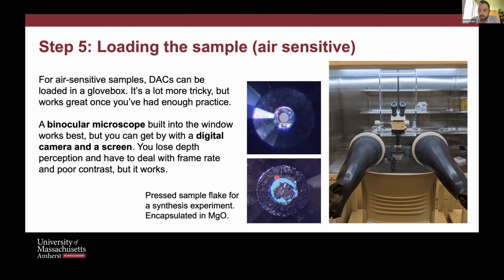I'm showing a picture. So again, this is not really relevant to this workshop because it's not a single crystal. This is a pressed flake of something that we then did laser heating on at the APS, but this is actually encapsulated in a sandwich of those MgO discs. And that's something that is easier to do in the glove box than liquid loading or even gas loading.